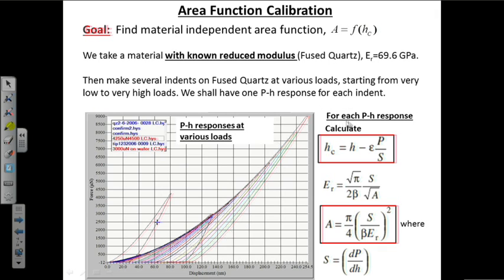Now, for each P-h response, we calculate the contact depth hc from this relationship, which is h, the maximum depth, minus epsilon multiplied by P over S, where S is the stiffness and P is the applied load. The epsilon is also a material constant, which could be obtained from the indentation data books, and also the area under load A could be obtained from this relationship, which was shown in the previous slide.